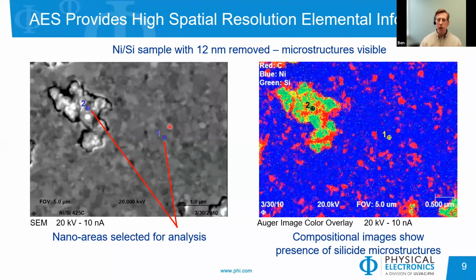And if we do Auger mapping, we can see some different features of, in this case, red is carbon, green is silicon, and blue is nickel in the 100 nanometer type of range and below. So again, getting very good spatial resolution with Auger.